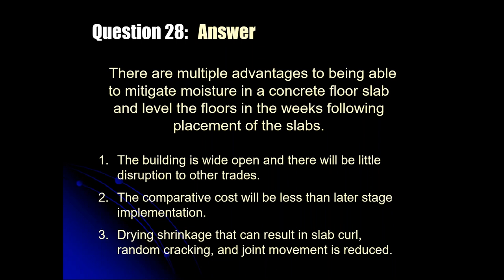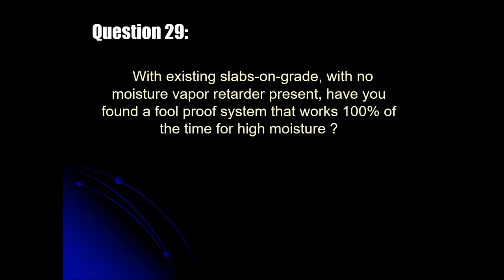The other benefit that you can get: slabs curl, crack, and warp due to loss of volume. By sealing the slab at an early age, before it's had a chance to go through a significant volumetric change, we have the potential of minimizing random cracking, joint movement, and warping. So there are some distinct advantages to being able to successfully install a moisture mitigation leveling system at an early stage.